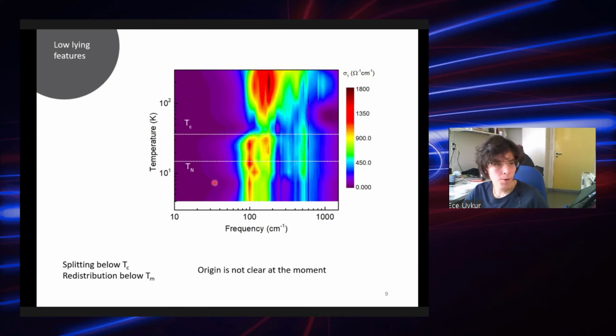And at the europium ordering temperature, basically some sort of redistribution is there. So the intensity in the low energies increased a bit more, and in the high energies it decreased a bit more. At that time, we had a suspicion that maybe there are some europium bands, not necessarily f bands, but a europium band that sits very close to the Fermi energy, and then when the Fermi energy starts to gap with the superconducting transition, we start to see these double transitions between these bands and so on.